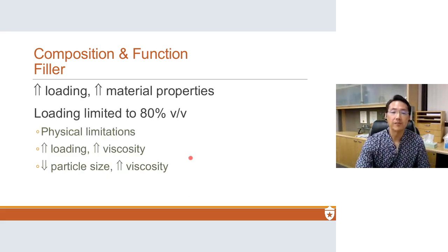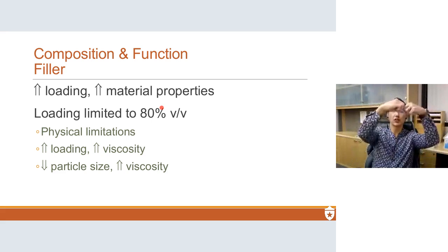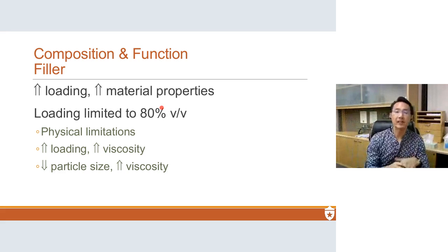So with the filler, okay, if you increase the filler loading, it increases basic material properties in general. Okay, so one of the objectives of having a dental composite is to load it with as much filler as possible. However, the limit is about 80% volume to volume. If you had filler particles exactly the same size, then it's limited to 73%, I think 73 or 74%, just because of geometry. So you have this, and if you assume they are circular too, they're like this, stacked next to each other, you're gonna have gaps in between. And so there's a physical limit to this, okay? Now, they have other ways of increasing that, but in general, it's limited to around 80% volume to volume because of the physical limitations.